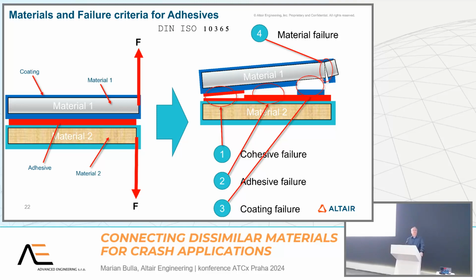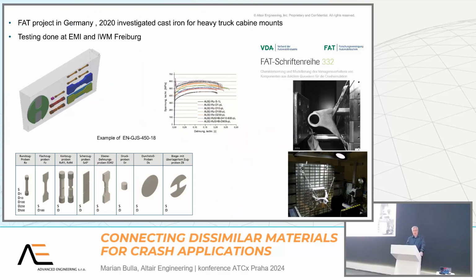This can lead to different fracture patterns. Cohesive failure, for example, which is here. Adhesive failure, which is here. Coating failure, which can occur here, and the material failure which can occur here. So we have to model all these individual materials and failure criteria and test them separately to have a validated model. This is normed in the standard ISO 10365, so you can read how it is defined. And we did these tests.